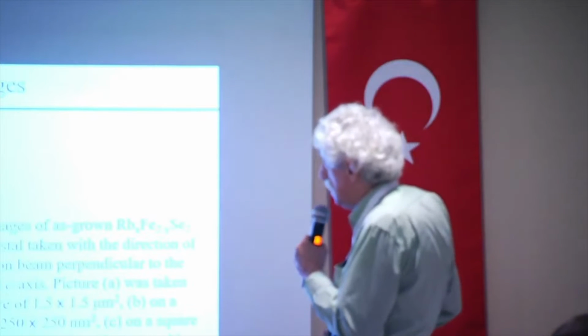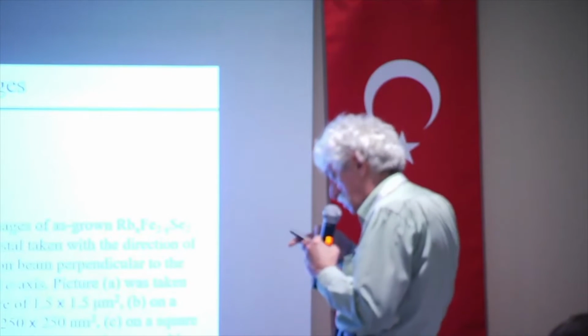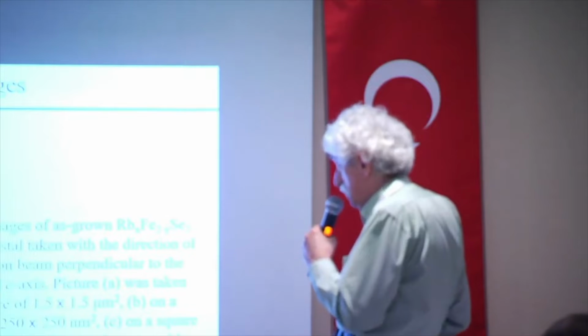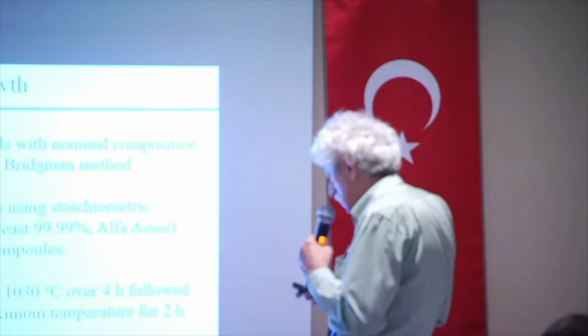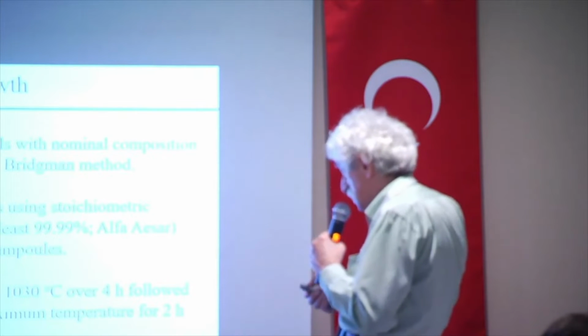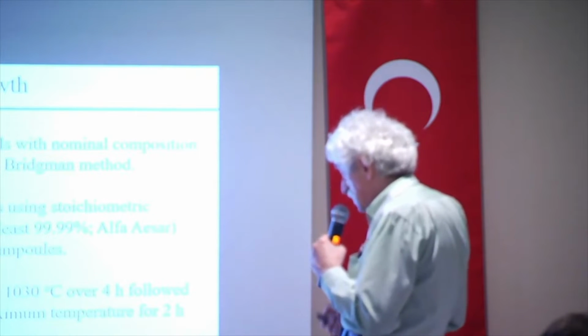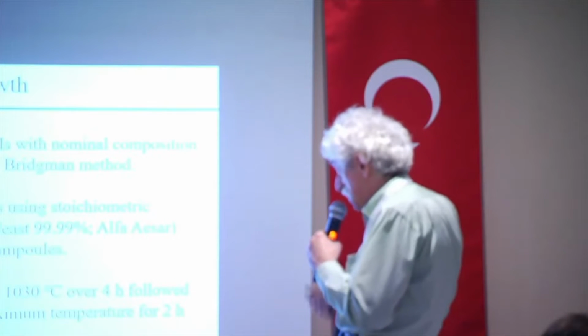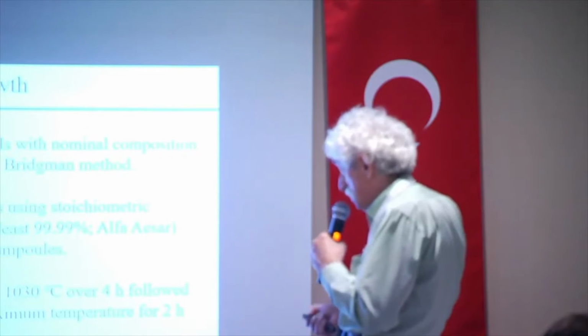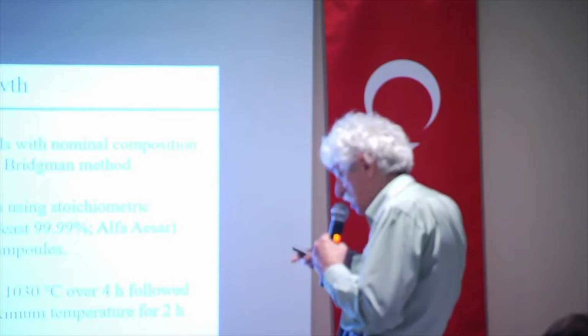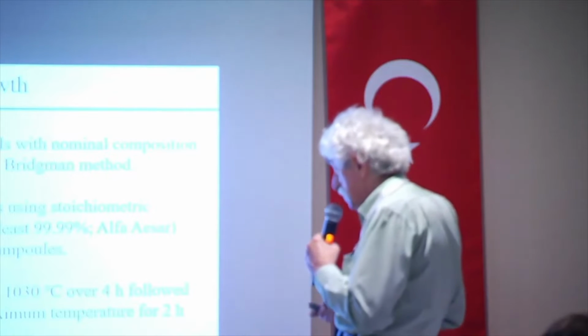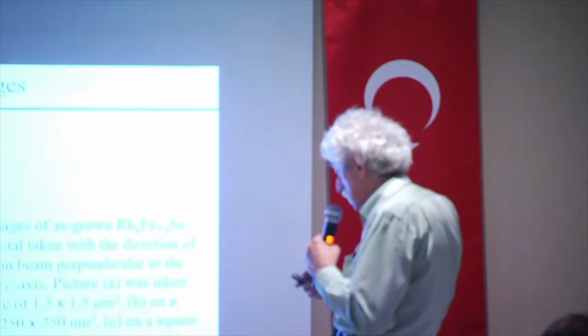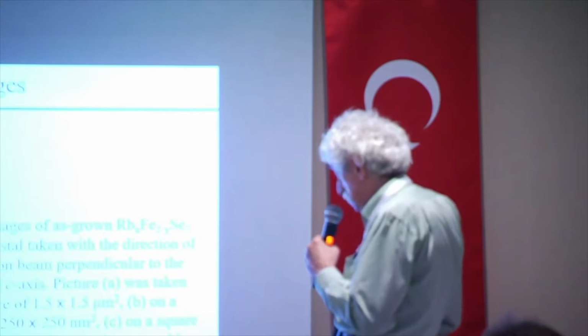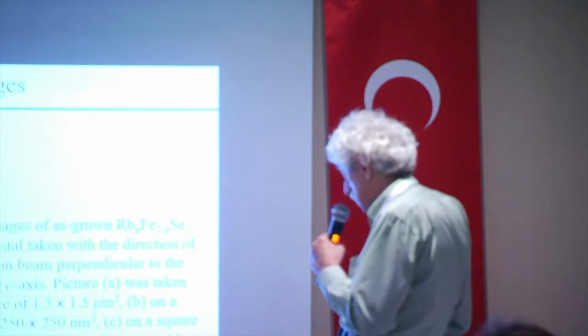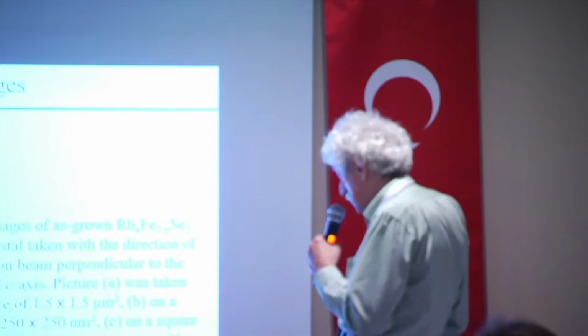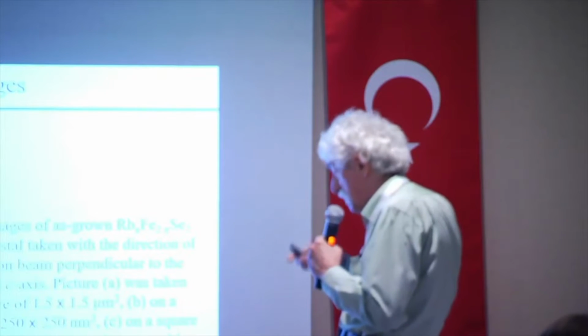And you can see this phase is a scanning transmission electron microscopy image. Here is a description of how the crystal is grown, but this is for technique. If somebody wants to repeat the measurements, they can look at the details. The most important thing is that just by growing these crystals, you can get at least two phases of materials.